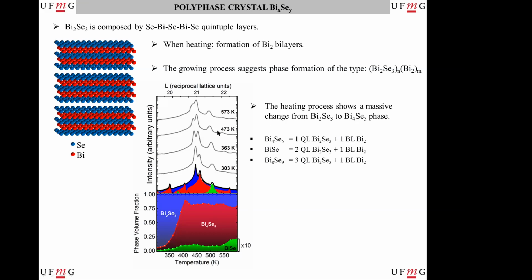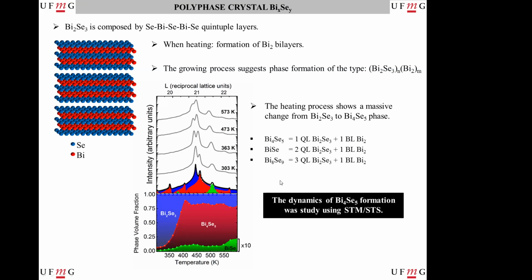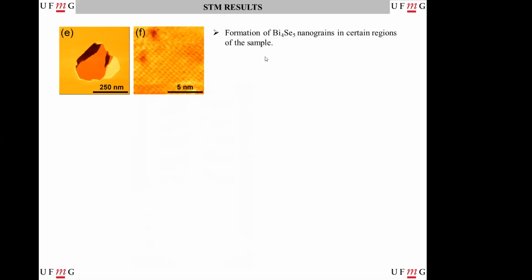So what we did was take this sample and put it in the STM to study the dynamics of this Bi4Se5 formation using STM and STS. In the STM results, we saw that the Bi4Se5 appears as nanograins in the matrix of Bi2Se3. Here we have, for example, an STM image of atomic resolution of Bi4Se5, and here is an example of a grain that you can find on the sample.